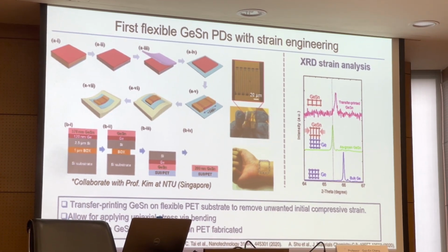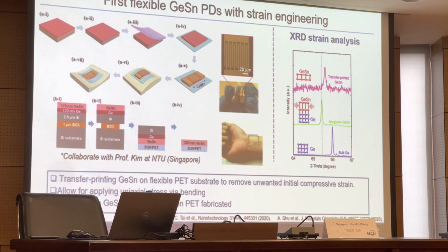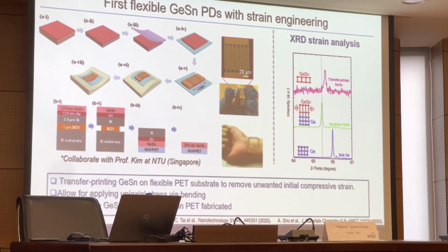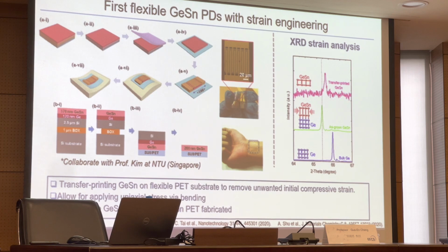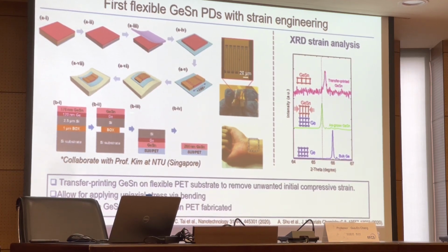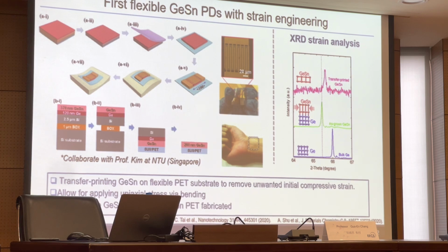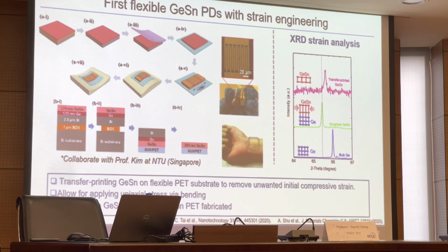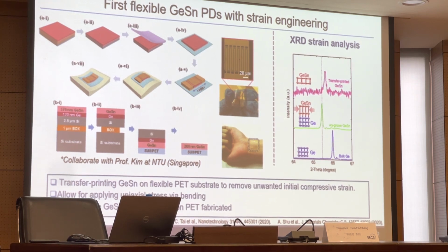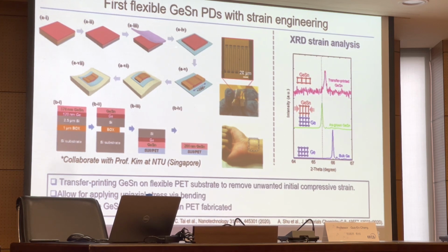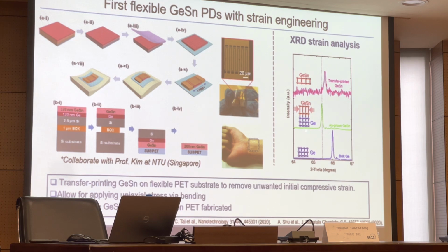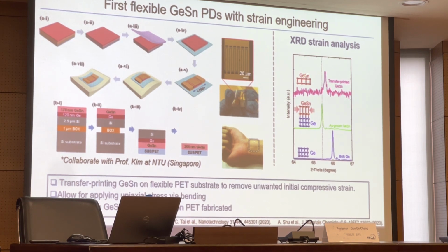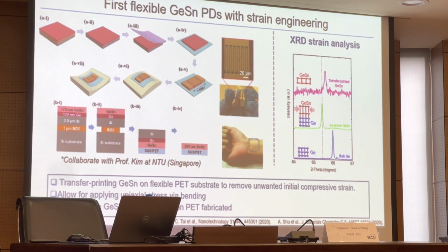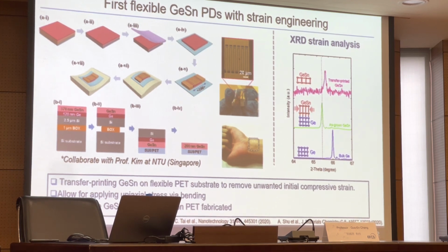There are more advantages than just transfer printing germanium tin onto a PET substrate. First, when we grow germanium tin on a germanium buffer, there is a residual compressive strain in the germanium tin layer, which is not preferred because it increases the bandgap energy. By transferring germanium tin onto the PET substrate, we can relax the compressive strain and achieve a wider photodetection range.